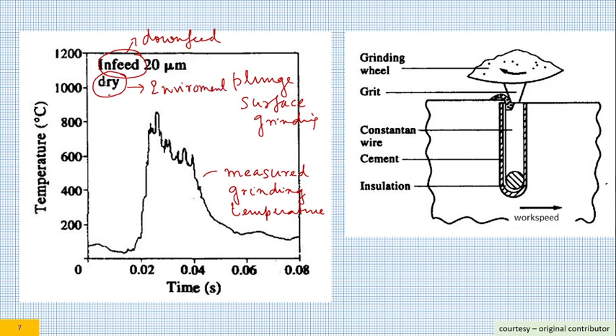However, this method can also be applied when you are applying coolant lubrication. As you can see, the maximum temperature is around 800 degrees centigrade, and this was measured in the first part of the 1990s, so 1990 to 1995, during that time in our laboratory. So this was developed and implemented, and measurements were taken in our laboratory.